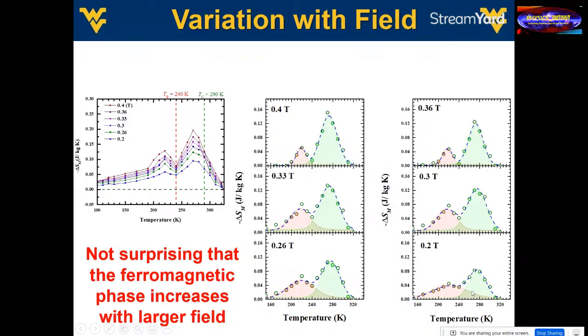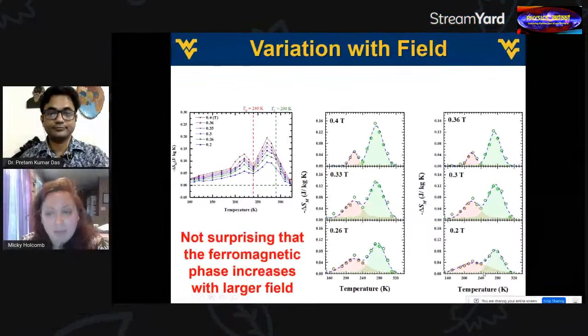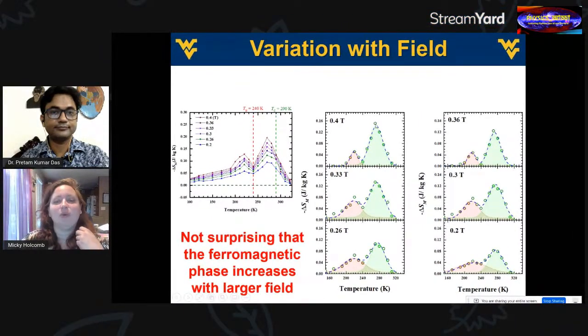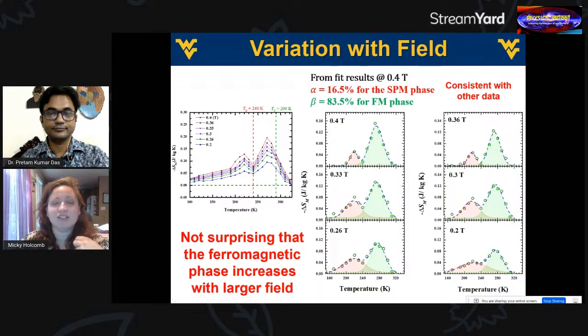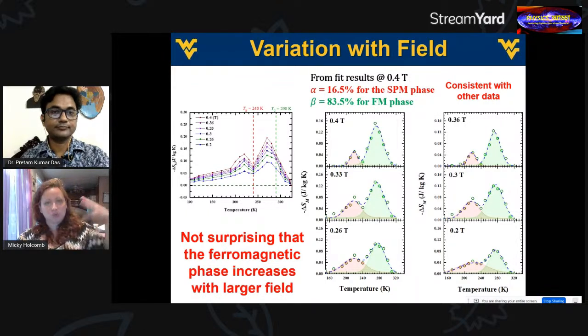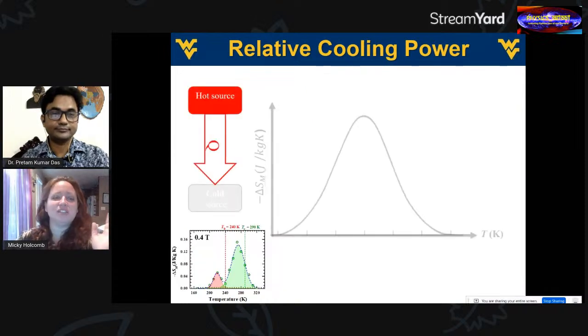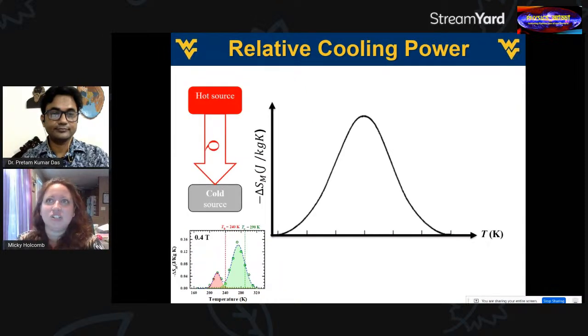And you'll notice that how much I have of each one depends on the field that I apply. So at these lower fields, this red region becomes more dominant in the system. Whereas at higher fields, the ferromagnetic region dominates, and that ratio between the two is pretty consistent with some of our other data. So we've been able to look at the phases, and this kind of leads us a little bit to using this technique for potential cooling.